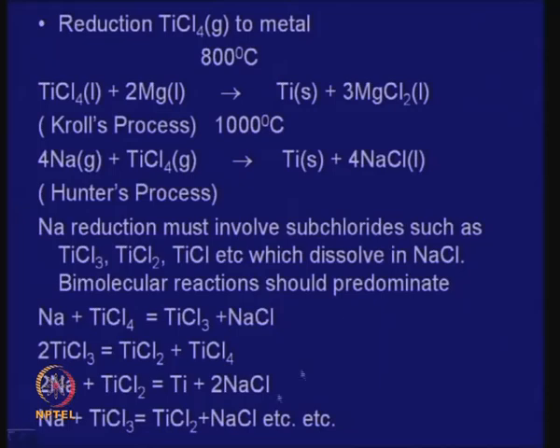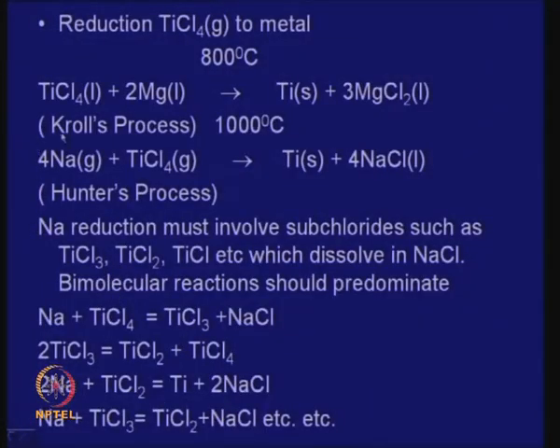Here is the explanation of something that looks illogical if you do not go deep into the mechanism. The proof is that the sub-chloride phases have been detected in small quantities in the sodium chloride melt. When it comes to the magnesium reaction, it is a termolecular reaction, but everything takes place in the liquid state — titanium is produced one particle at a time, producing a dispersion of titanium particles.